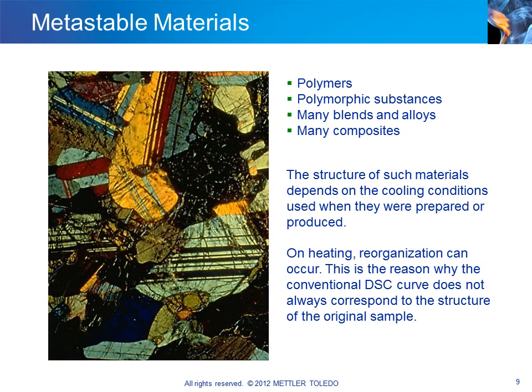It is always advisable to use a wide variation of heating and cooling rates when kinetic processes significantly affect the formation of structure in the material under investigation. In such cases, the structures depend on the cooling conditions and are often metastable. The structures can change as a result of a temperature change or during isothermal storage. Polymers are examples of materials that form metastable structures. Due to their molecular structure, they produce only small crystallites on cooling from the melt. The size of the crystallites depends on the crystallization temperature and hence on the cooling rate.